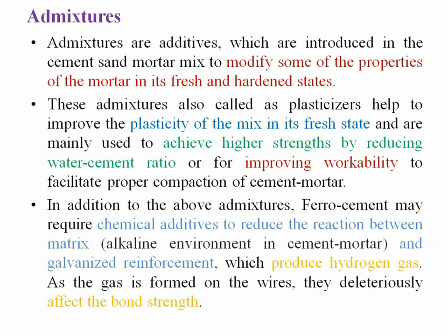The chemical reaction between the matrix and galvanized reinforcement produces hydrogen gas. As this gas is formed on the wires, it deleteriously affects the bond strength.